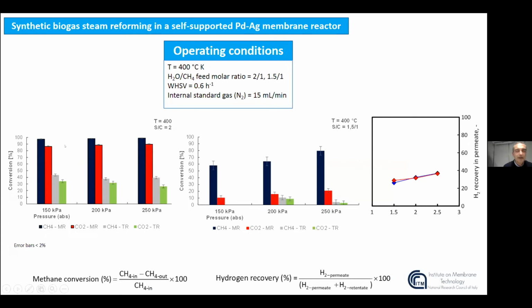And in general, the increase of pressure determines two opposite effects on the membrane reactor system. The positive one is related to the shift effect, because the higher the reaction pressure, the higher the hydrogen permeation driving force, because more hydrogen is forced to permeate through the membrane. More hydrogen consequently is removed from the reaction side, and the reaction is shifted towards the products with an enhanced conversion.